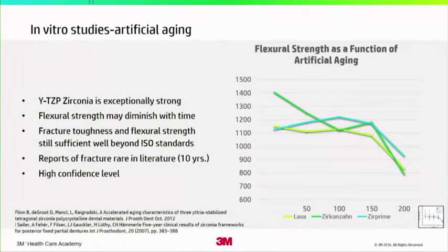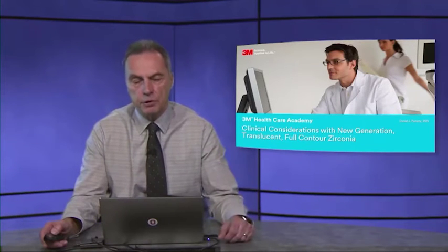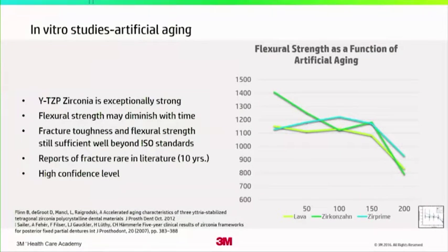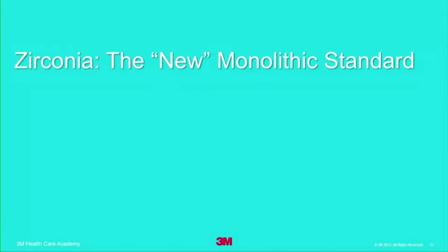Now, there are other studies that have been around for quite some time, and this is an example of one where flexural strength is a function of artificial aging. As you might expect, the material will drop from its initial strength to another lower level. But on the other hand, we need to understand that flexural strength is perhaps not the best clinical indicator in terms of how we would choose a material, because we will discuss at a later point how to rethink what we're contemplating when we're selecting a material, particularly when strength is the critical factor. If you do a literature search, you'll be quite surprised to find that fracture is very rare in the literature. And I think based on this, we can have a high confidence level with regard to the material's usage and application itself.